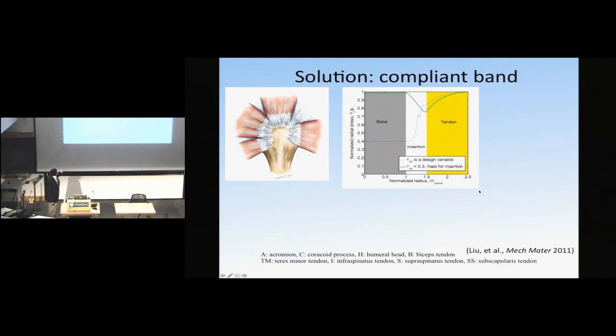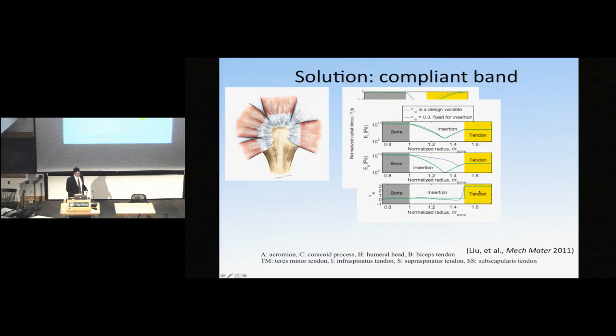But then if we allow the modulus of material to shift as a function of radial position, we can actually end up with a stress distribution where the stress inside the bone and at the bone insertion site interface is lower than the remote stress. This is the maximum radial stress. This comes, of course, at the cost of increasing tangential stresses, sort of like a porthole in a ship. And indeed, the material property distribution. These are now moduli stretching from bone to tendon, the other way around. So the moduli that achieve this are situations in which there is a region of compliant material between tendon and bone that allows stresses to be diverted from the radial direction to the transverse direction around the bone.